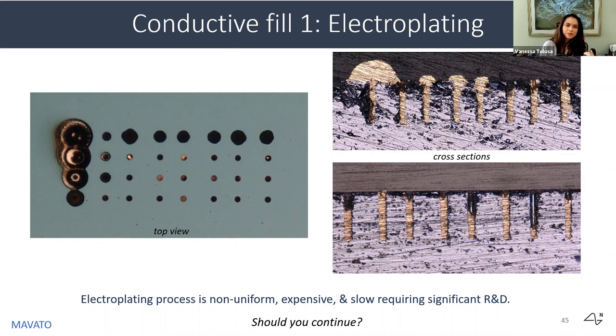But after quite a bit of effort, you find that the plating kinetics for gold and platinum, which are your target materials, are so slow it would take over a week per wafer to properly plate your vias. In addition, it's proving difficult to get uniform plating, as shown in these images of real samples. You see, we have overflow in some of the vias while other vias don't fill properly. And there are many other issues not even shown here, but in short, you're under pressure for time and decide that this option would require significant R&D and that you don't have time for that.